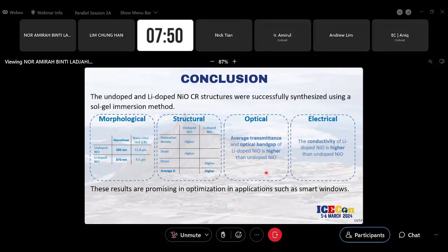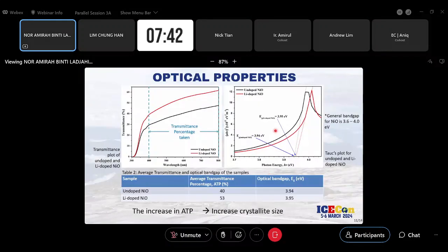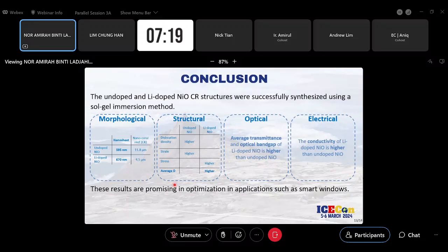So for optical properties, I plot a Tauc plot. This is the Tauc plot. So we found that the band gap of both sample falls within the maximum value of the general band gap of nickel oxide. This one. Lastly, for electrical properties, the conductivity of lithium is higher than the undoped sample. From here we can conclude the properties of nickel oxide could be improved with the incorporation of lithium as the dopant element. Further information about the result you can ask during the Q&A session, okay? As we're running out of time.